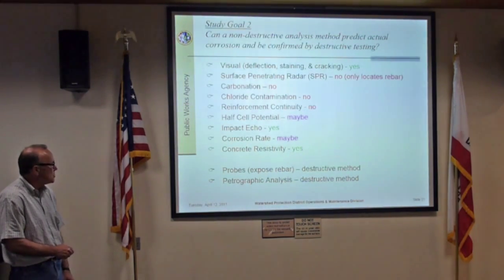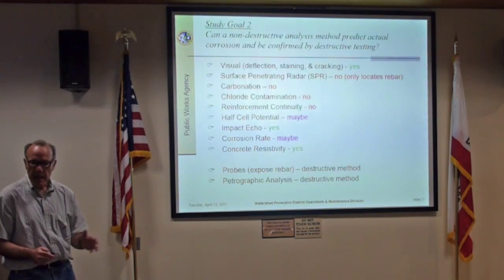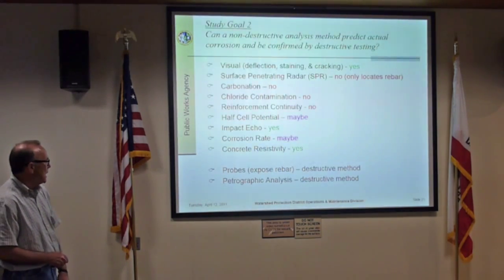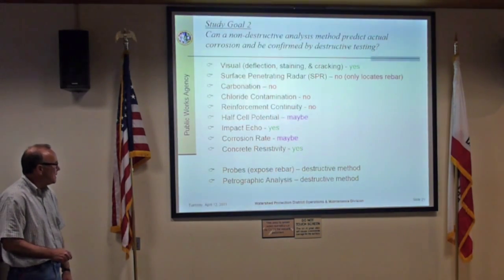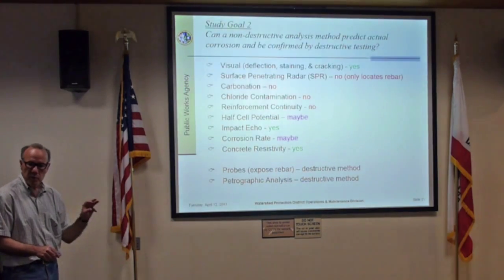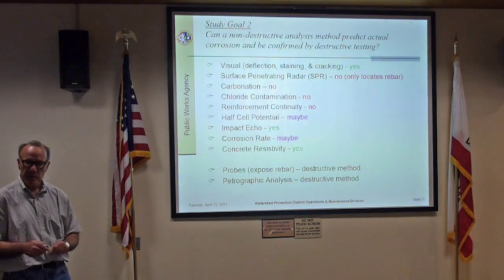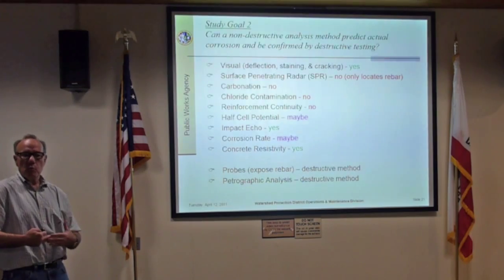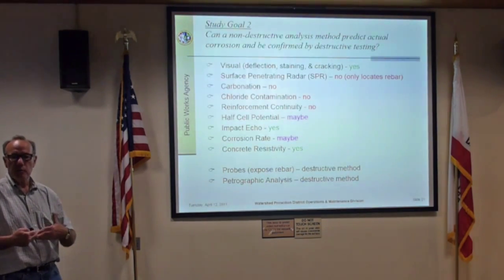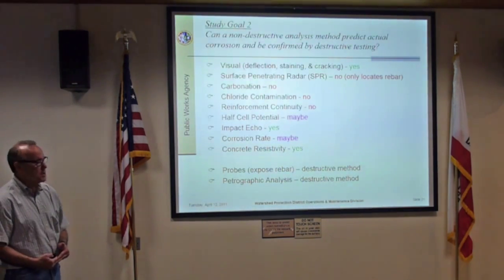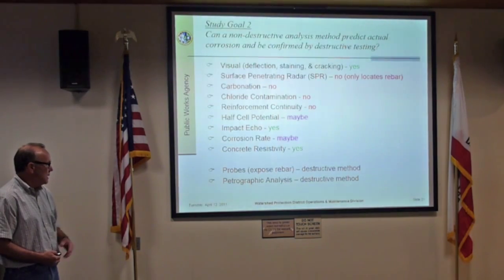It gave us some information. It was kind of a mixed bag of whether it told us something or not. Concrete resistivity was one of the easier tests. It was a pretty good indicator when we did that surface test of was there a lot of moisture in the wall, and therefore did it coincide with the corrosion rate?